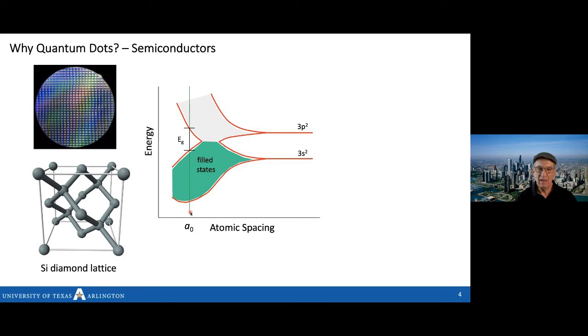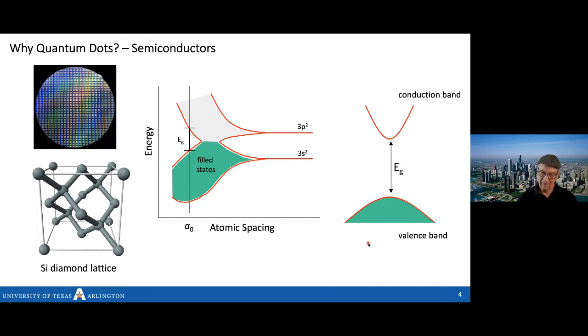And what we see then is the semiconductor behavior that we use all the time, which is filled states, so-called lower band, it's a valence band, it's completely filled. There's an energy gap, and then there's an upper band that's completely empty at zero Kelvin. When we change the temperature to room temperature, we see a few carriers up here and open spaces down below. So that looks like this. If we look at the shape of the bands, we have a filled band below, an empty band above, and an energy gap in there.